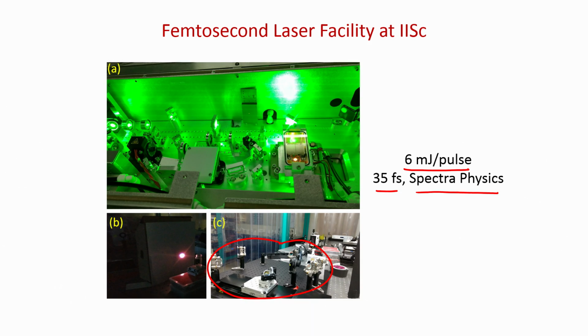So the bottom line of this whole module is that if we want to use a femtosecond pulse as a sophisticated heater, just to deposit heat energy, then there are some advantages and some reservations. The advantage is that it can provide a well-defined time window for the heat deposition, but the reservation is that there is a time period for which electron and phonon are not in equilibrium.